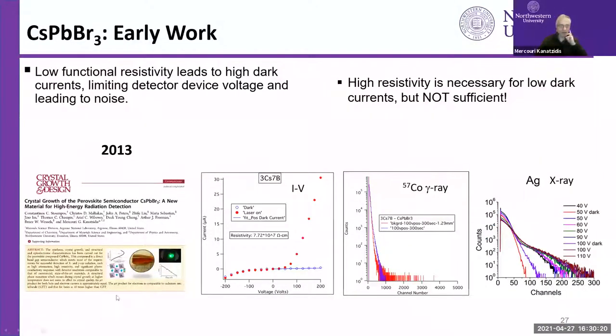So back in 2013, we published this paper for the first time identifying this material being promising for high energy radiation detection. And we published these IV curves with resistivity that was not very impressive, almost like 10 to the 8 ohm centimeter, but it was photoactive. This is the laser on, this is laser off. So it was photoresponsive with laser light. However, look at the gamma ray response, almost nothing. With dark and with the gamma rays on, no response, so it wasn't good. But it did have X-ray response. And we see here we're counting X-rays of silver, which is about 24 keV. And that is what made us think that this material would be promising for that.